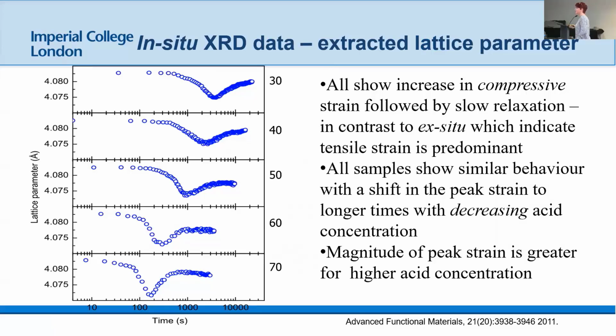You get a different measure if you do this in situ or ex situ, actually. So it's really important that you are careful about how you're doing these measurements. And that's partly to do with adsorption and dehydration as you pull a nanoporous material out of the solution. In fact, there are some beautiful videos online by Gleiter, that as you take one of these foils out of solution, they visibly flex, right, as the charge exchange causes this stress in the surface. And of course, if you're really unlucky, they just fall to pieces because they're very brittle, because they're in this extraordinarily highly strained state at small grain size.